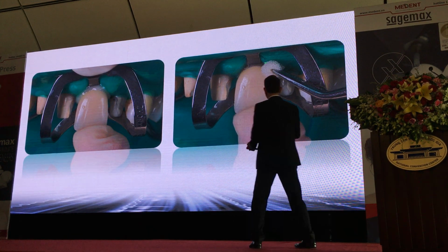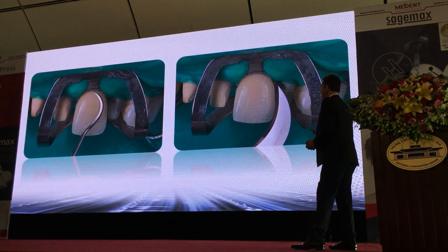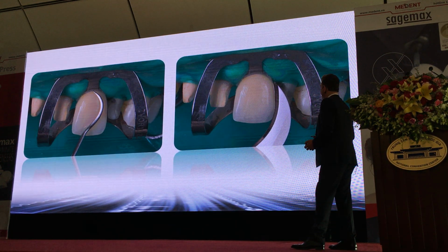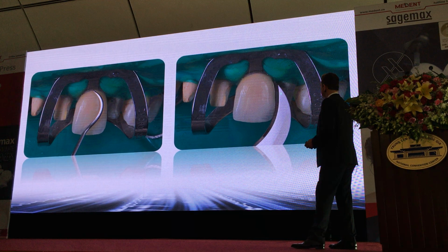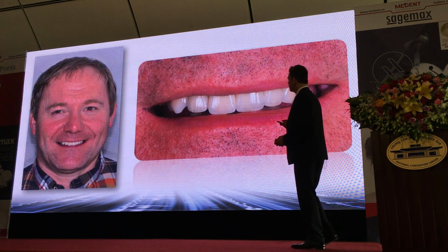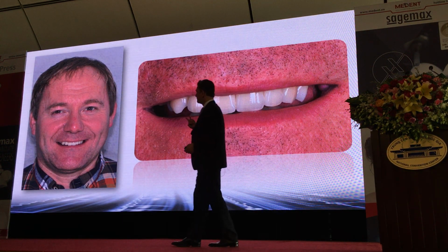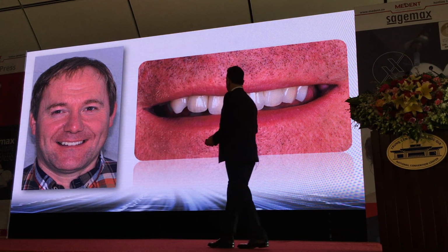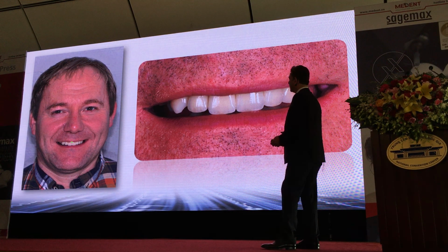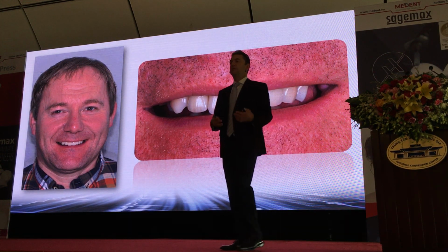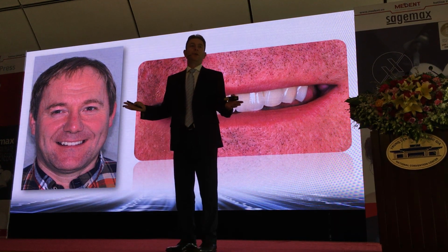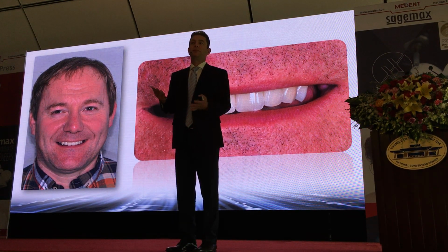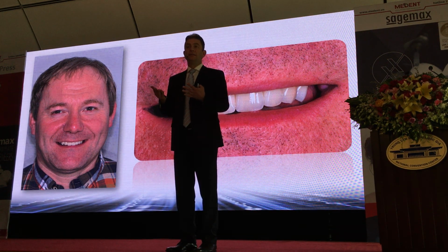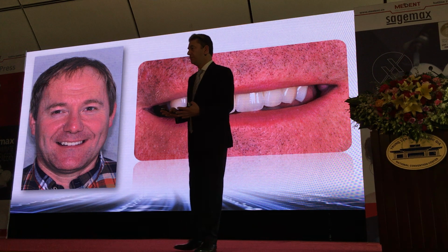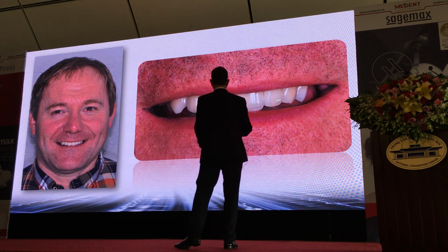In this case, you can see you use this foam pellet and remove it here. Yeah. And then, you can see these are after light curing, we can use a scalpel just to carefully remove some of the excess which might still be there. But you can see he is quite happy actually with the result here. Of course, we could make it even brighter, but I think he's an older gentleman, right? So we don't want to give him a B1 shade or something like that. He looks ridiculous. Sometimes patients are requesting this, and if they insist on it, I give it to them. But sometimes it looks a bit difficult. But in this case, you can see it's quite decent.